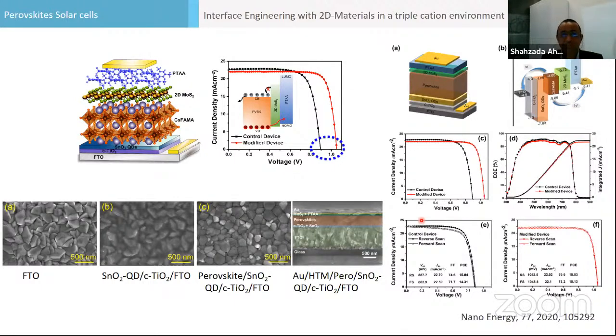We are all very much familiar with 2D materials. This is the 2D material we call graphene, but we want to think beyond graphene. Beyond graphene, we use molybdenum sulfide. It's also a 2D material, which also has a band gap. We put it as a special layer because we saw that there was a big gap between the valence band of perovskite and the HOMO of the hole transport material, and this big gap causes energy losses. So we put a thin layer of 2D MoS2, and this has seen a significant jump in the VOC. You can see from 900 it goes to almost 1080 millivolts. This is a big boost, and you can see an FTO here with a quantum dot.